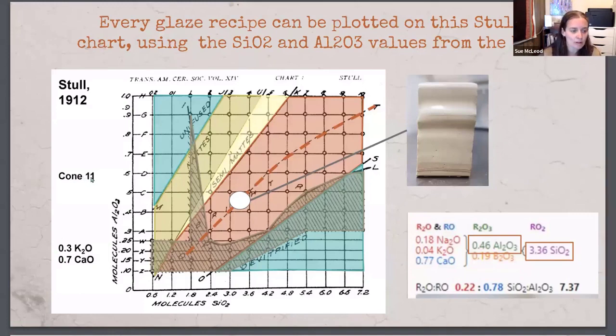He was firing Cone 11. He didn't have boron in his glaze. So this isn't to be taken as the be-all and end-all. Not every matte glaze is going to fall in the matte region, but it's just an example of the patterns. In the art of glaze chemistry, you'll do experiments that take you from the left side of this chart to the right, and you'll see how a glaze moves from matte through the glossy. And then we've got the underfired section over here on the right.